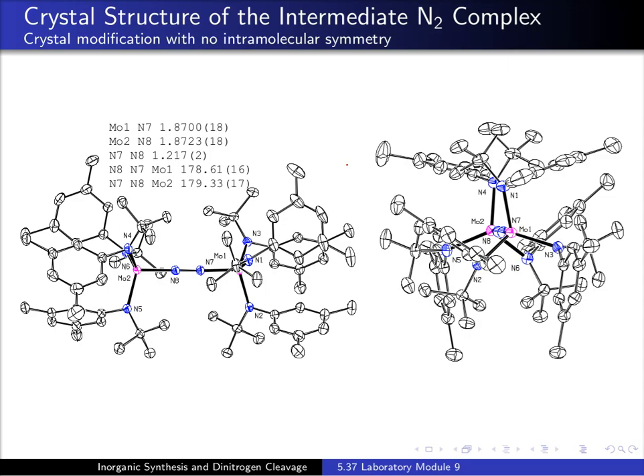This is the crystal structure obtained by single crystal X-ray crystallography of the bridging N2 complex intermediate. We found one important structural parameter here, that the NN distance is only about a tenth of an angstrom longer than it is in the free dinitrogen molecule. Here it is about 1.2 angstroms. That's the NN distance between the two nitrogen atoms from the N2 molecule that is serving as a bridging ligand in this dinuclear dimolybdenum complex.